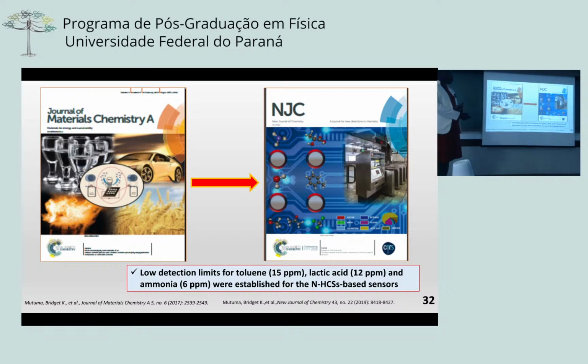And after that, we also collaborated to look into doping of hollow carbon spheres for detection of volatile organic compounds. And we found that by just doping the hollow carbons, we are able to decrease the detection limit towards ammonia, toluene, and also lactic acid. So this is work that we've done on hollow carbons so far. And with the structure of the hollow carbons, I got excited. Can we use the same principle for metal oxide?